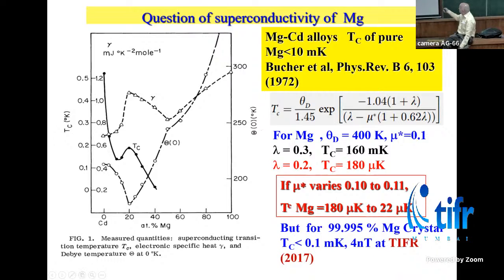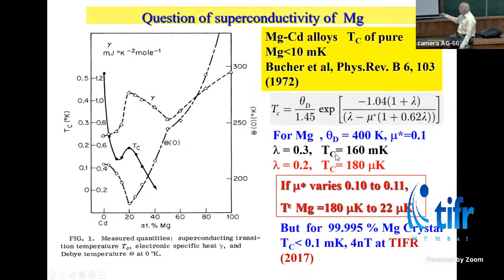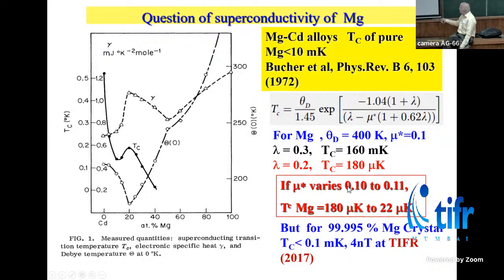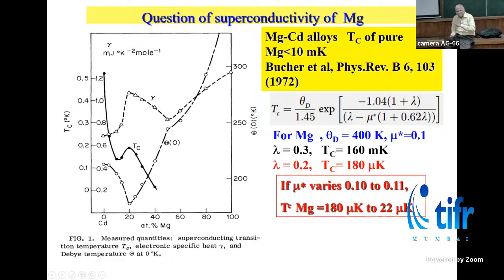So then what happened is that you apply the McMillan theory. If the lambda, the electron-phonon coupling constant, is 0.3, it is 160 millikelvin. If it is 0.2, it is 180 microkelvin. But more importantly, if the mu star varies from 0.1 to 0.11, it's so critical that you go from 180 microkelvin to 22 microkelvin. So we made a very pure crystal and tried to search down to 100 microkelvin. So that was again a failure story. We could never get magnesium superconducting. So at least up to 100 microkelvin, it is just not superconducting.